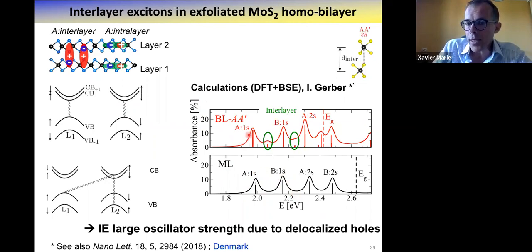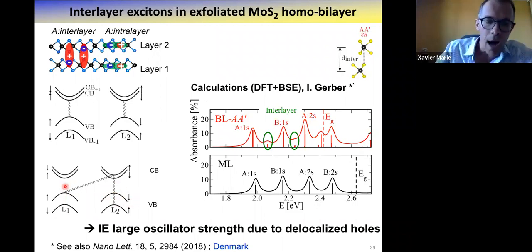And when you do this on bilayer, you find again the B exciton, the A exciton, but in between, you see another transition. By analyzing this calculation, we assigned it to an interlayer transition, which connects a carrier with the same spin. But the key point is that this interlayer transition has a large oscillator strength, thanks to the hole tunneling or hybridization, whatever, of the hole state.